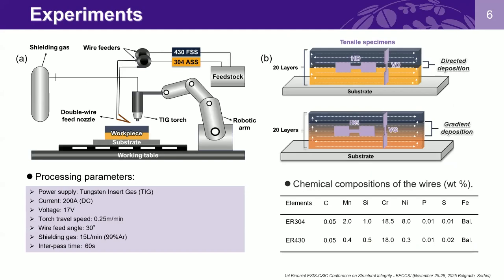This slide shows the experimental procedure. Figure A illustrates the schematic diagram of the dual wire system. The corresponding processing parameters and the chemical composition of the two wires are listed in the table. Figure B illustrates the tensile specimen, and the position of the tensile specimen extracted from the directed deposition sample and gradient deposition sample.